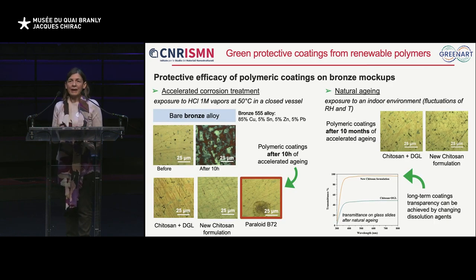We performed in parallel accelerated corrosion treatment in the presence of hydrochloric acid, but also natural aging in an indoor environment without control of temperature and relative humidity to promote the degradation. And so after 10 hours of accelerated aging treatment, we can see that the uncoated substrate is completely degraded. By comparing the formulations, we can see that in the case of the commercial benchmark, we observe the presence of some spots due to the formation of alteration products.